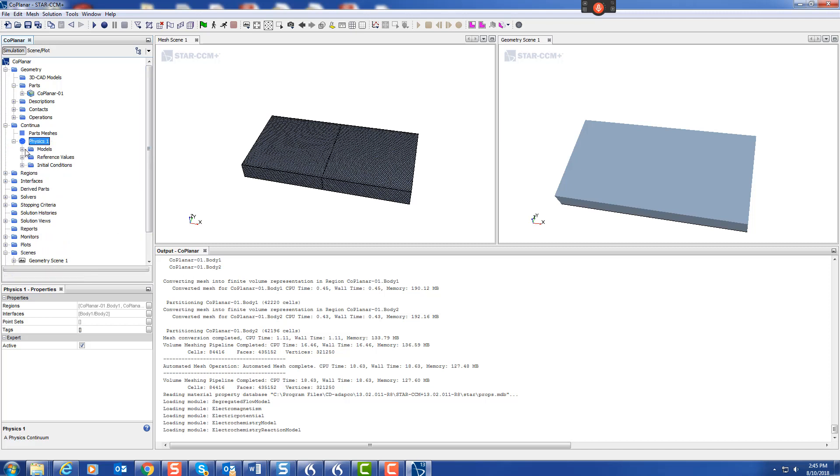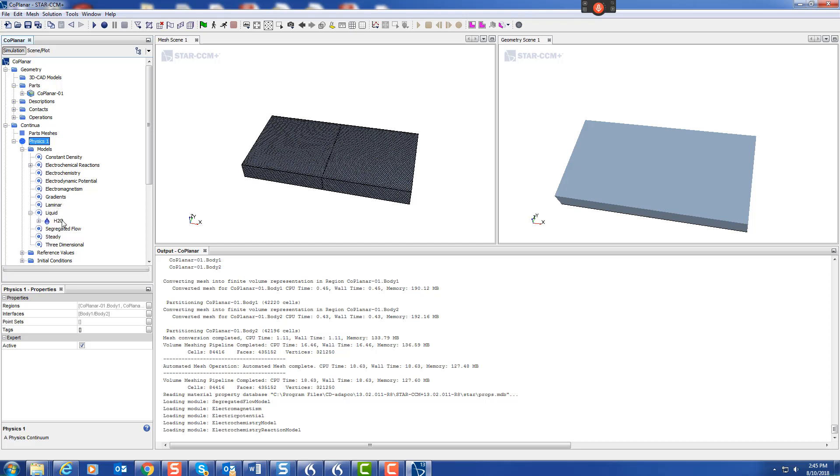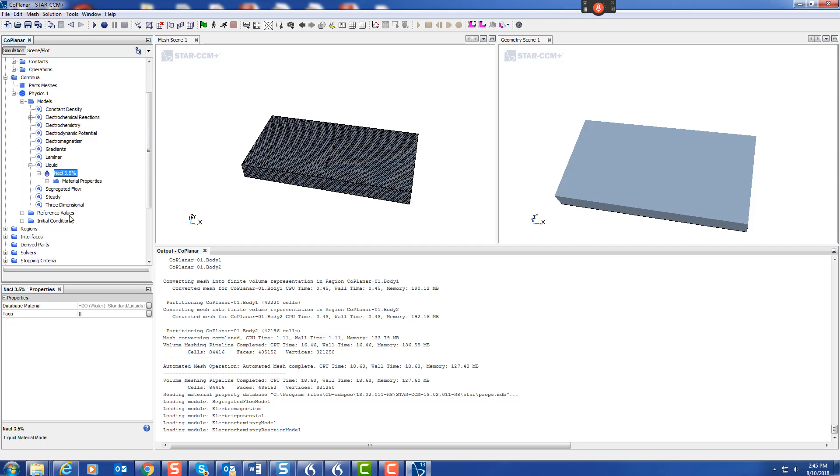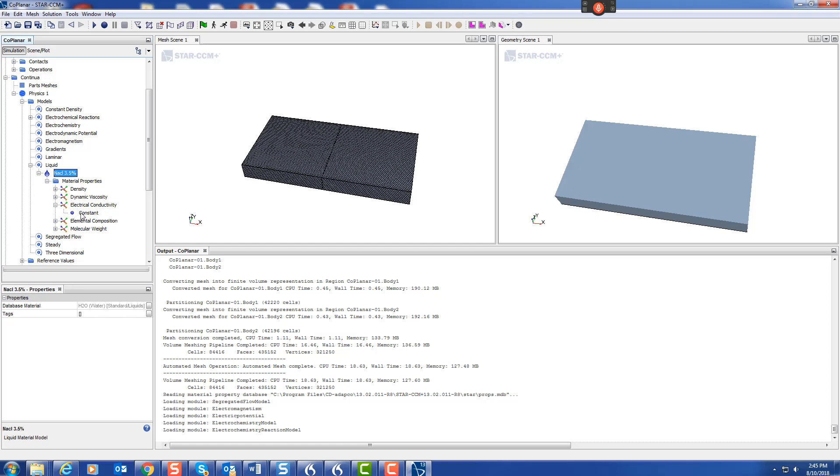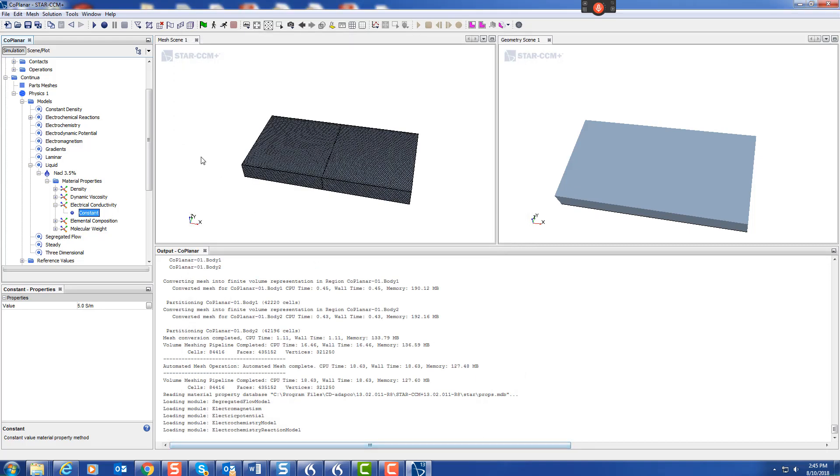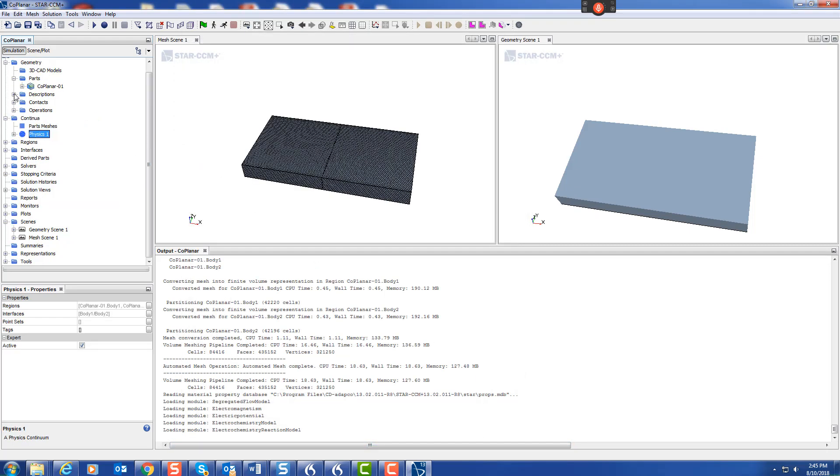While we're here, let's go to the liquid. Default is water, and all our polarization data is NaCl 3.5%, make a note of that. We'll need to change the electrical conductivity. You could change other things, but this is the important thing for the moment. That's just tap water, so let's do five. There we have it, so we've got our media in there.